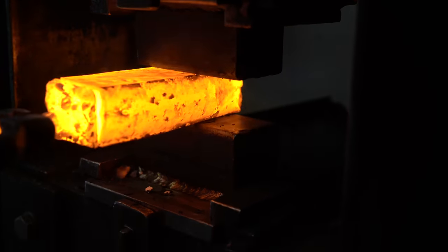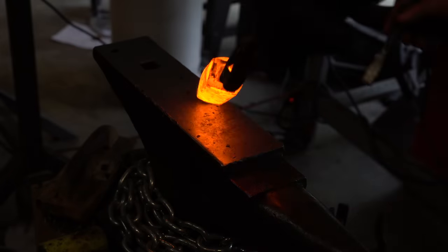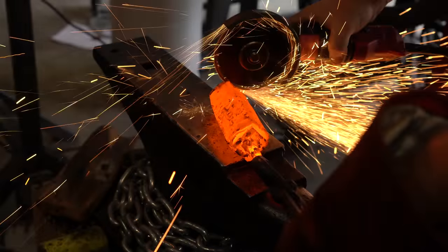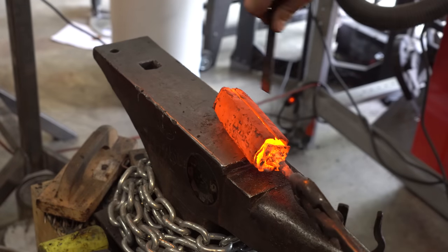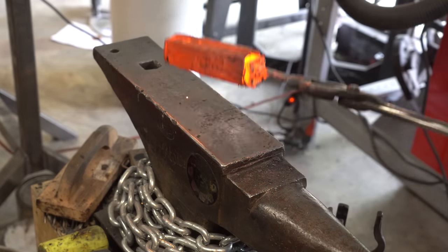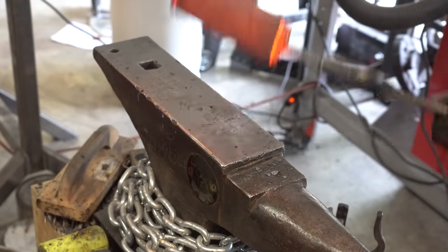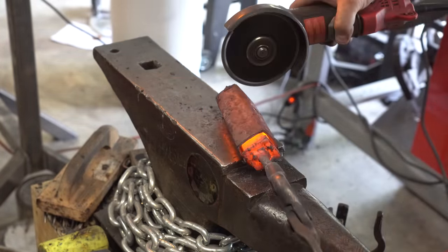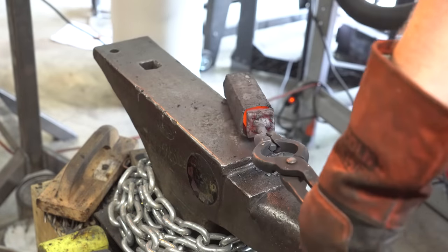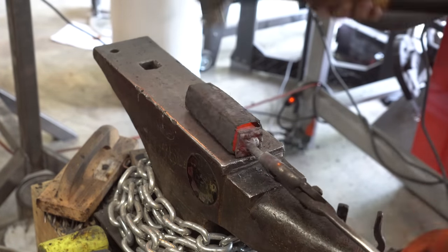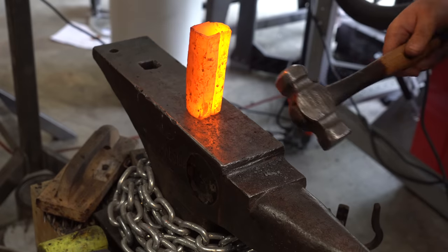That's because the can is bulging, so we know the can is not sticking to the contents at least. The one problem that you're going to see soon is that I used mild steel as the end caps and those end up welding to the interior of the billet. This makes it much harder to get the can off. Normally when I do this, the can just slides right off. But because the end cap is welded to the contents, it wasn't so easy. When I finally realized the problem, I just ground off the cap and it came right off. Even with this little issue, it only took about 5 minutes to get the can off. That's how it's supposed to work.